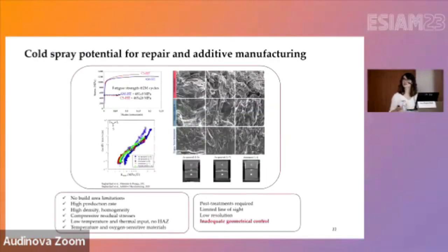So we have been bragging about the possibility of using cold spray for structural applications. It has comparable fatigue performance with respect to other additive manufacturing techniques. There's no size limit. There is very high production rate. So these are what is differentiating cold spray with respect to other additive manufacturing technologies, apart from the fact that we have very low heat input. But one of the main bottlenecks of cold spray that has hindered its establishment as an additive manufacturing technique is that we still have inadequate geometrical control.